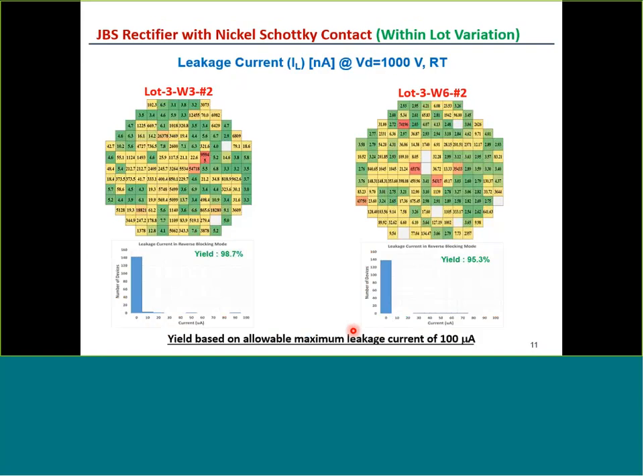The leakage current can be a challenge for Schottky rectifiers, and this requires proper design of the JBS structure and a good process for making the nickel Schottky contact. We have achieved this, and we have low leakage currents in the nanoamp range, and the values are all well below the leakage current of 100 microamps. So our yield is generally more than 90%.